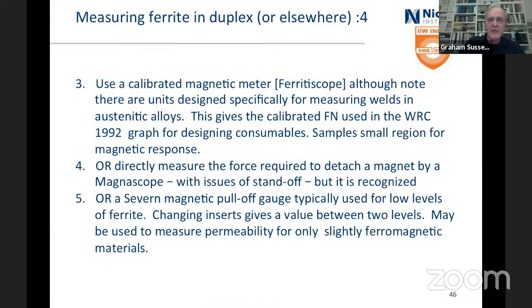The alternative is to use a ferritoscope. There are units actually which are designed specifically for measuring welds. The initial ones were a bit big. They're still moderately big, but they give a calibrated ferrite number. Note, ferrite number is not the same as ferrite percent. Talk about that in the next slide. Used by the Welding Research Council 1992 graph for designing consumables. Samples quite a small region around them for magnetic response, but it is not as small as a heat affected zone.